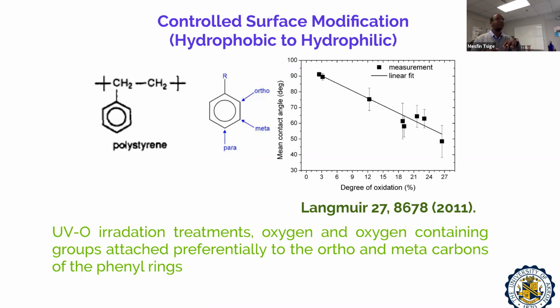So when they put a water droplet, even if the average degree of oxidation is around 12%, that water droplet could be on 12%, 14%, 15%. So when they take the average, they get larger fluctuation. And if they didn't have this last experimental data, it would have looked as if it has saturated. But the last data point made them conclude that there is a linear dependence. But this is more a hypothesis.